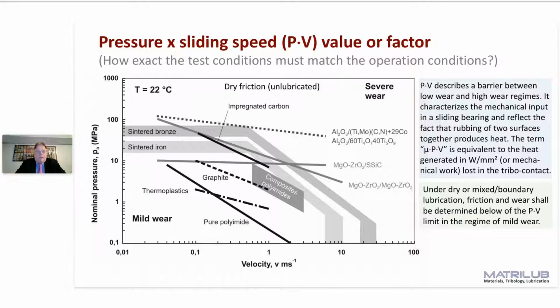It means even if you have a very low speed, 0.01 meter per second, there is a maximum nominal contact pressure you cannot exceed, because the material begins to flow in the tribo contact. Even if you have a very low contact stress and you go on the x-axis to high speed, 10 or 20 meter per second, you can also not exceed this sliding speed, because the microasperities may melt, evaporate, or creep. So you have two border limits which can be predicted, and in between you can exchange pressure and velocity.